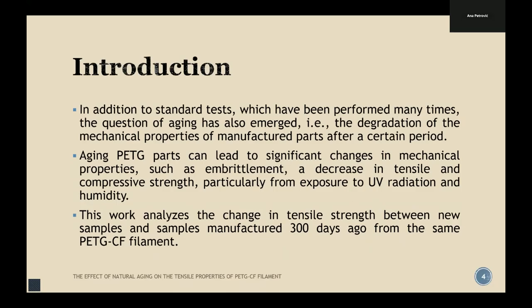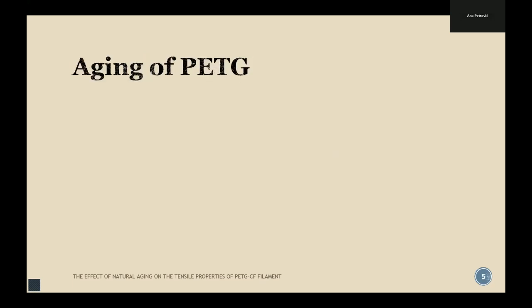This work analyzes the change in tensile strength between new samples and samples manufactured 300 days ago from the same PETG-CF filament. CF is for carbon fiber reinforced filaments, used to get better strength, but it can also affect the ductility.